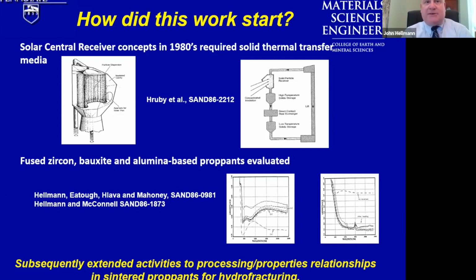The charge, the batch of ceramic particles that would go into the system was on the order of 12 million pounds. That's a large volume of materials, so it needed to be relatively inexpensive, obviously very refractory, and mechanically and thermochemically robust to withstand repeated cycles over a lifetime of several years. So we examined particles that would be available from the abrasives industry, and there was no shortage of materials that we could use there that had the requisite properties of refractoriness and high strength and even solar absorptivity. However, due to the nature of abrasive particles, they were angular.